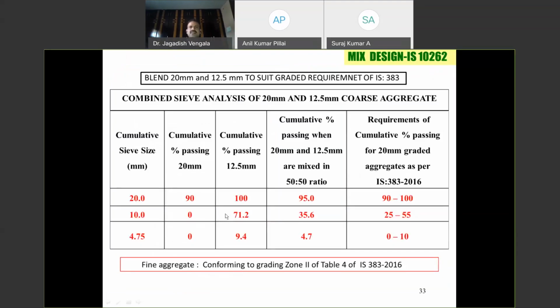So this is the single graded aggregate. Whatever aggregate is there, 20 and 12.5, this is what we see. So this is the cumulative percentage passing of both 20 and 12.5 in a 50-50 ratio. So this is satisfying the grading requirement of IS 383. So what you have to do is blend both 20 and 12.5 to suit the grading requirements. And fine aggregate is conforming to zone 2.